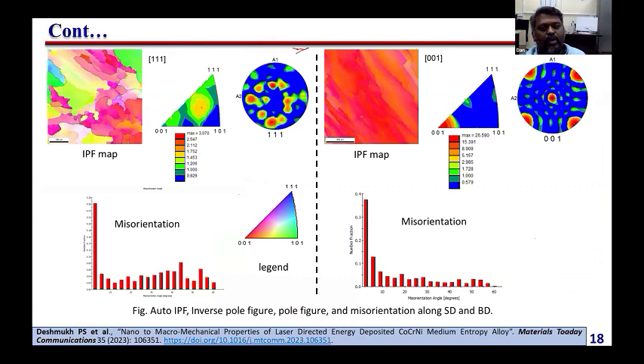We could deposit at least 20 layers, 20 to 30 layers. We also took samples in different directions, which we call the scanning direction and the building direction. Along the building direction and the scanning direction, we took the samples and characterized the microstructure by EBSD.